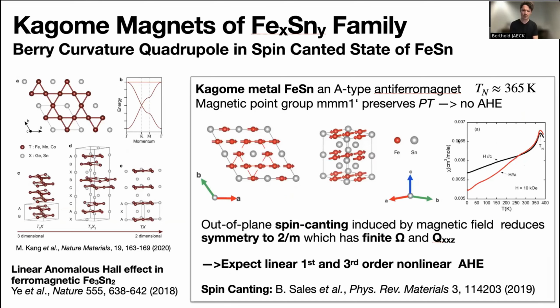To demonstrate this phenomenology, we're interested in the Kagome magnets of the iron tin family. What makes these materials so interesting is basically summarized here in this overview on the left side by Mingu Kang's work. What is quite interesting about this family is that you can very accurately control both the electronic and magnetic properties of these materials by combining different types of elements like iron, manganese, cobalt, germanium, tin, but also changing the stoichiometry. For example, the 3-2 stoichiometry of iron tin gives rise to this out-of-plane ferromagnet that we just talked about, which features a relatively large anomalous Hall effect. On the other hand, when you look at a 1-1 compound like iron tin or later cobalt tin, you have a different spacing.